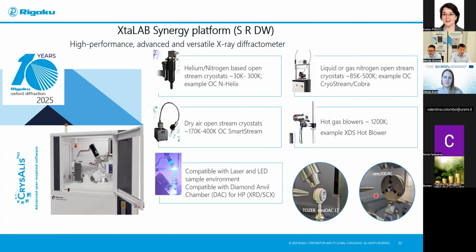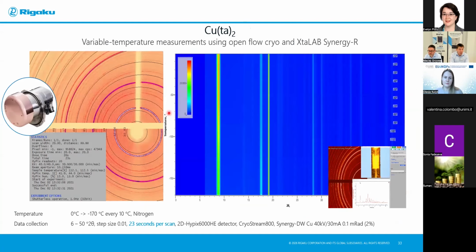This is the 120 DAC, which gives a very large opening for your crystals, 120 degrees, which allows you to access the sample and collect very complete data. It's also compatible with the Synergy systems. So usually you see that I'm presenting a rotating anode, so the Synergy R platform, because it provides much more intensity, allowing very quick measurements. So I took the same powder that we already discussed, copper MOF, and I checked what's happening at low temperature.